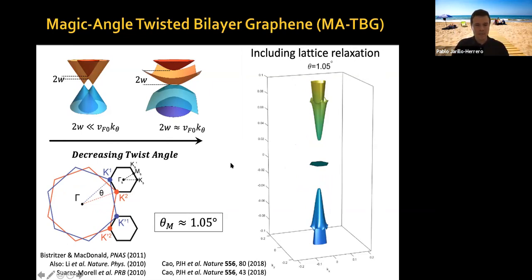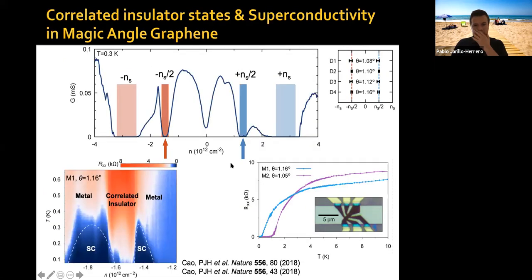So this is something that led to our papers in 2018, where we discovered correlated insulator states when you put half as many electrons in the valence band or in the conduction band of these flat band systems as you could. You have an insulated state where you would expect in single particle physics a metal. And then these correlated insulator states were bounded by superconducting domes. By now these results have been reproduced by a dozen groups or so, and it has even extended in very interesting directions, including topology, etc.